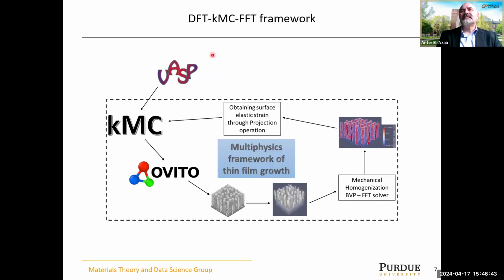This is the multi-scale framework that we use. The engine, or simulation tool, is a Monte Carlo framework, but as the film grows, it has elastic effects. We tie those strain effects to the growth through the effect of strain on bonding and hopping energies for atoms on the surface. And these fundamental energies come from density functional theory, through the VASP code. So we have multiple codes and multiple physics tied together: elasticity, diffusion, and bonding, and then the parameterization using electronic structure methods. That is basically the framework.